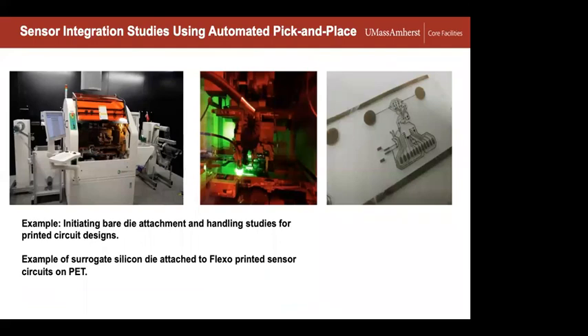And this just, again, shows kind of both the Besi automated pick and place tool. The center is kind of the inside of it with the images and all the sophisticated machinery. And the right is just an example of a flexible printed circuit, which we had on a continuous web. So we loaded that on, and just in a simple demonstration mode, showed that we could just continually pick and assemble single individual silicon components onto something as it was moving along. And again, this unwinds, and it'll index to a certain point, stop. The piece of equipment will populate that region, and then will index to the next area. And I believe that's about 12 to 18 inches in length each time.